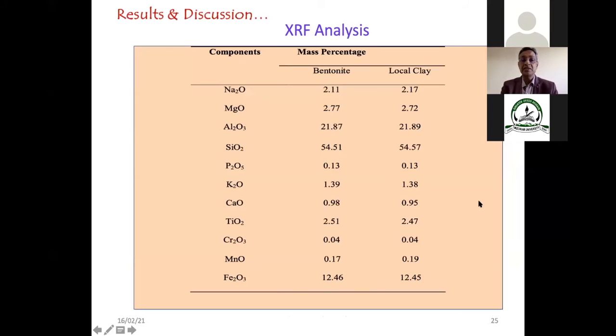This is the X-ray fluorescence data by which we have estimated the percentage composition of the different oxides, for the bentonite as well as for the local clay. You can see that the different values are given here. Mostly it is alumina and silica, which are very high in content, and then some iron is there, and some titanium oxide.